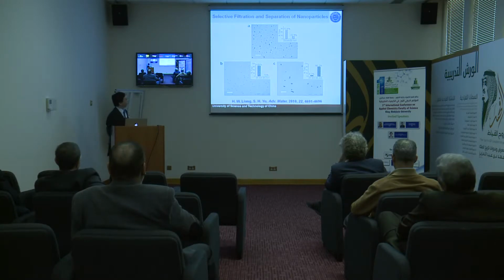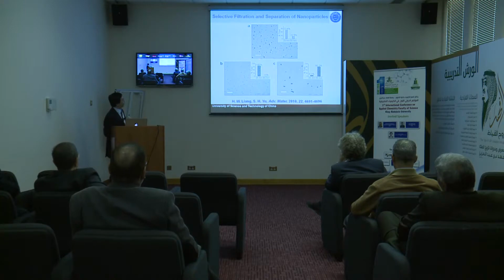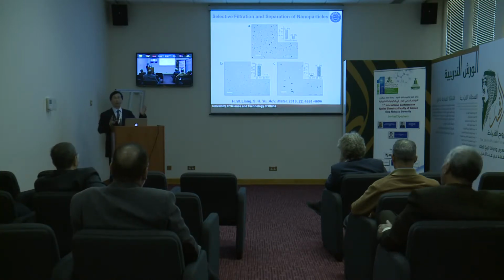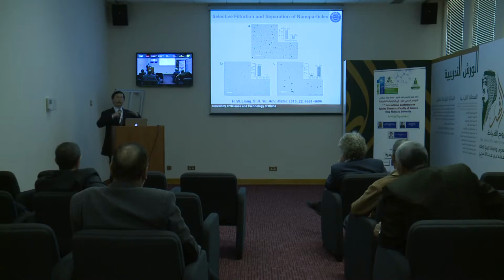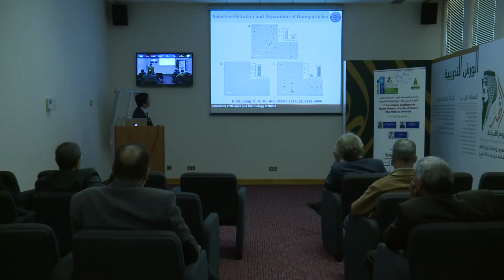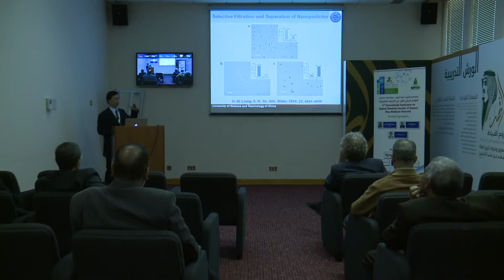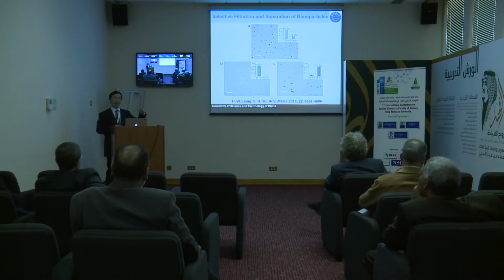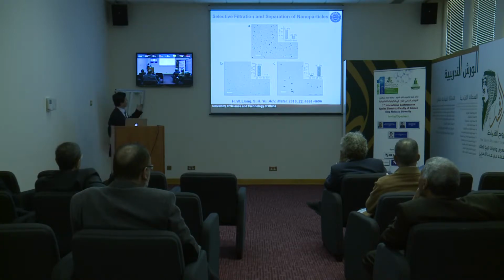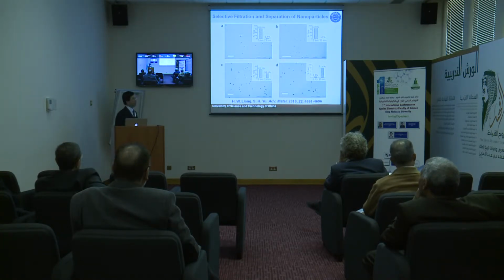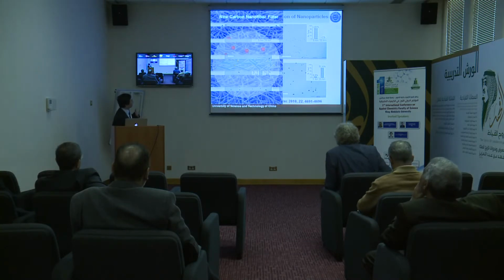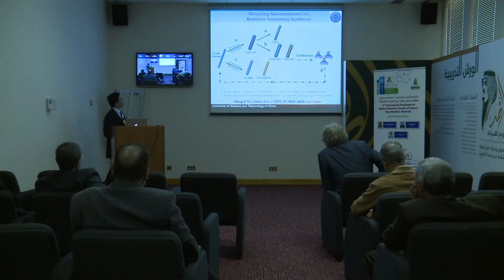So for filtration applications, we can use our hydrophilic fiber membrane as a filter. You can separate nanoparticles of different sizes using such a membrane, because the membrane has different porosity. Here is some data showing you can indeed do this filtration. You can separate nanoparticles of different sizes in the range of a few nanometers to 100 nanometers. Also, the filtration is very good and very fast.